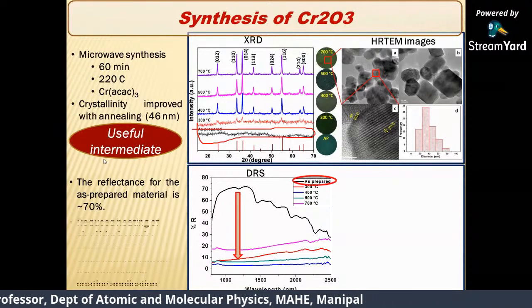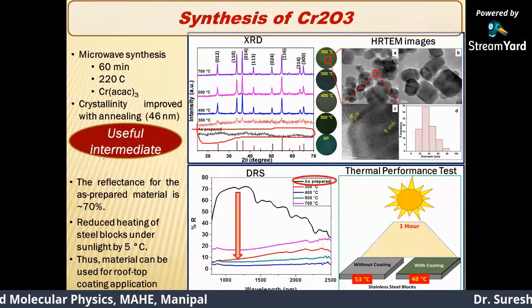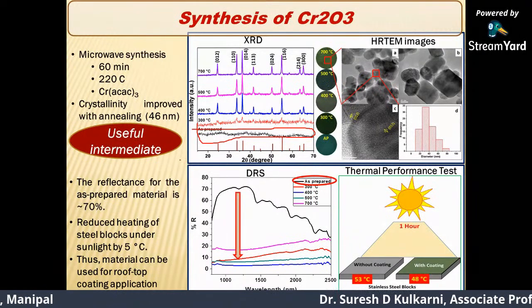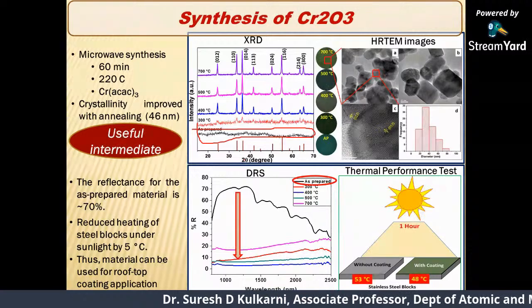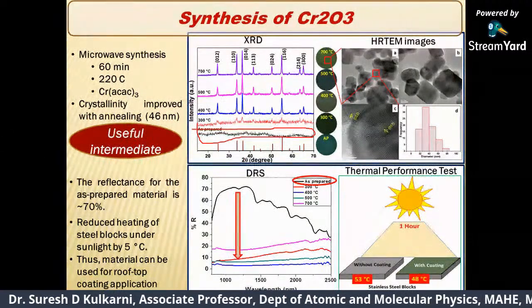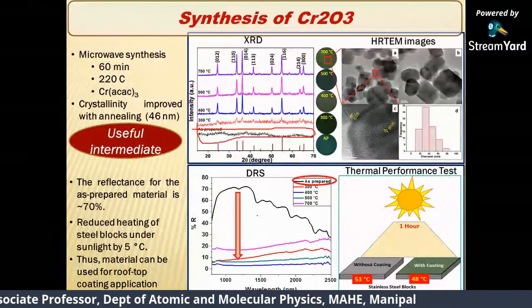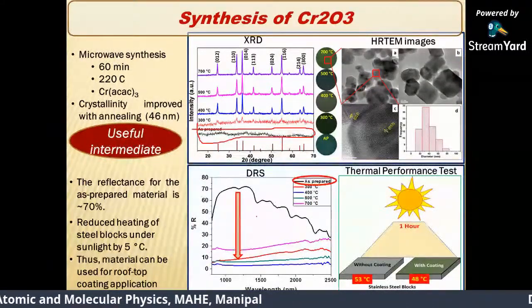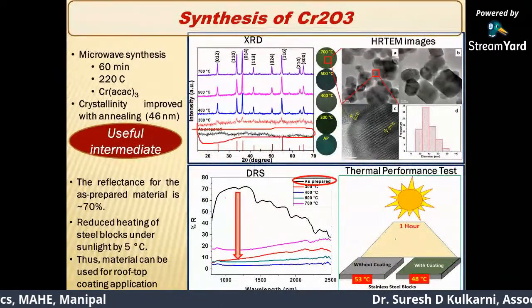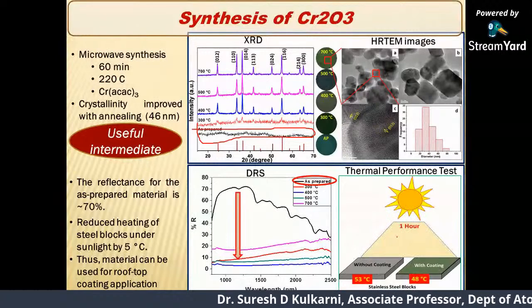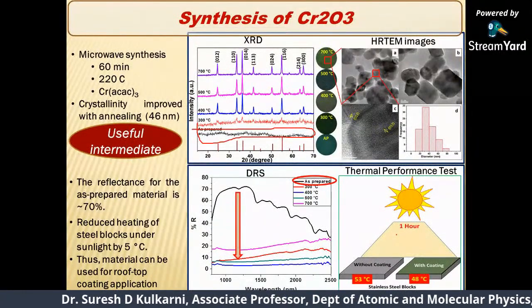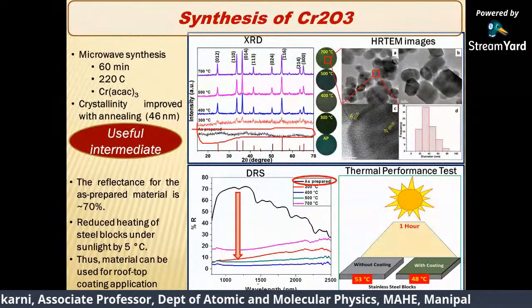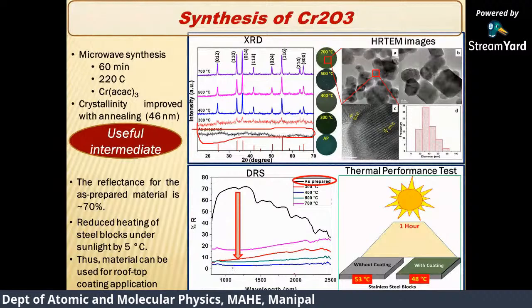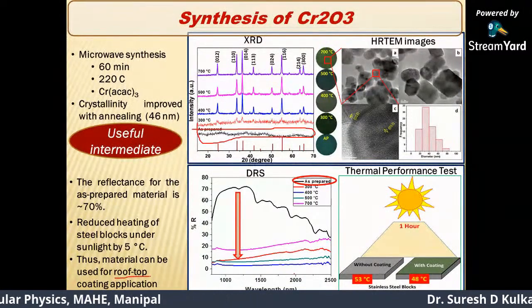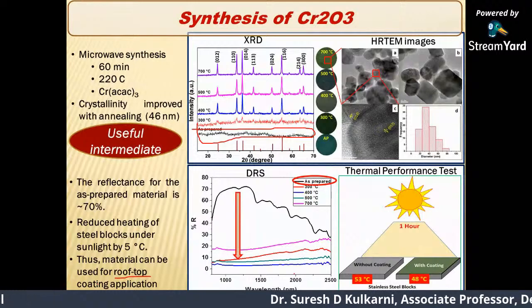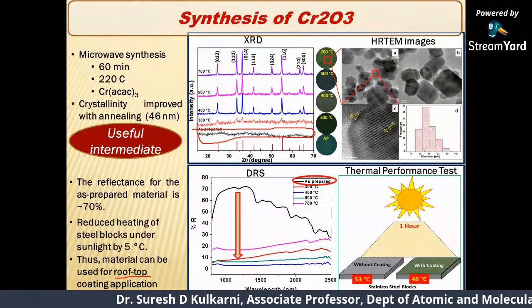So what we have done is, we have taken this material and a stainless steel plate. There is one stainless steel plate as such, and the other stainless steel plate was coated with this intermediate material. We kept them under the hot sun for 1 hour, and we see that wherever we have the intermediate coating, the temperature is about 5 degrees lower. That means this material can be put to use for rooftop coating applications. Wherever you have intense sunlight, the roof of the house gets heated, you can paint with this material so that the surface doesn't become hot.